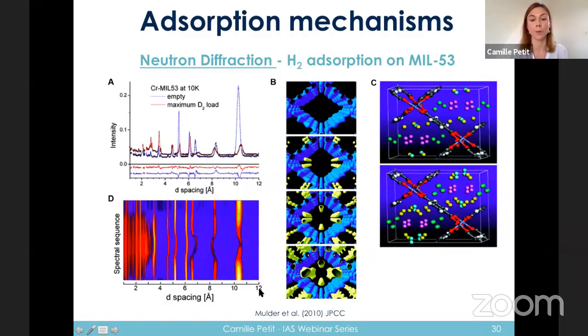And if you look at B here, that's a Fourier transform map in a way, where we can start to see the progressive adsorption of hydrogen within the pores of the MOF. And the hydrogen is what you see in yellow here. And the graph C here shows you the Rietveld refinement, where we have actual location of the hydrogen atoms within the structure upon adsorption.